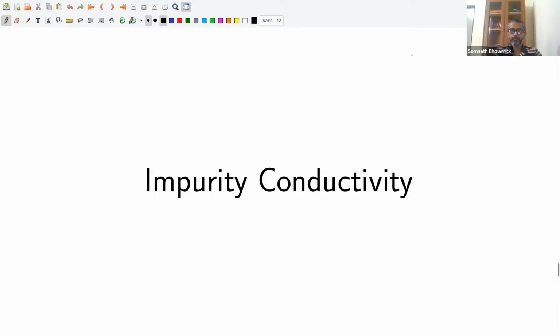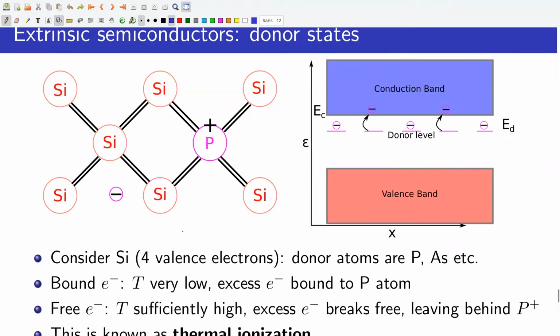In this lecture, I am going to discuss doped semiconductors. First, let us consider doping of an impurity atom of valence 5, like phosphorus and arsenic, in silicon, which has 4 valence electrons. We know that silicon has a diamond cubic crystal structure. Each silicon atom has a coordination number of 4. Each atom forms 4 covalent bonds, one with each of its nearest neighbors, as shown schematically in this diagram.